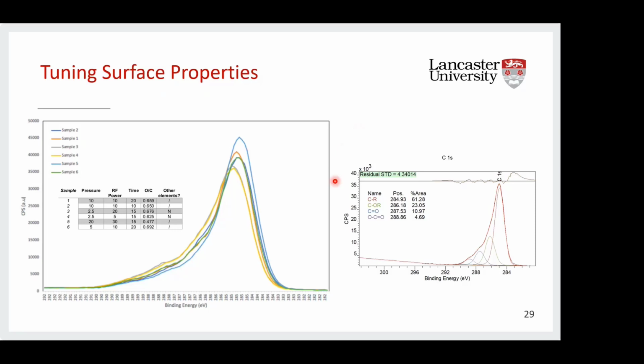Then there are the so-called high-resolution spectra for each element. So these are both C1s peaks. Then within these, you have peak analysis showing the different bonds. So if we first look at this overlaid spectra, you can see the differences that are occurring because you've altered those plasma parameters, so you can see these peaks shifting about.